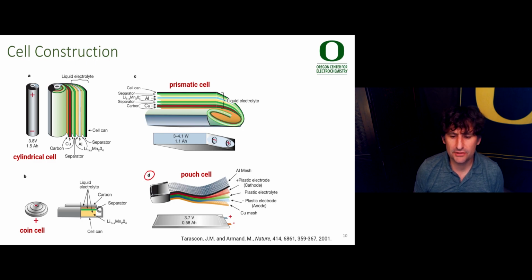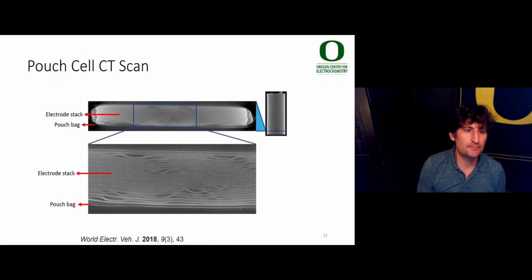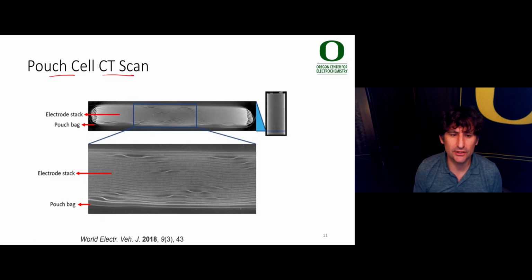And here D, the pouch cell, which consists of alternating layers that can be repeated multiple times to form the battery cell. Here's actually a CT scan of a commercial pouch cell that I found in the literature, and you can really see how the tabbing works here, connecting all the, for example, positive electrodes and negative electrodes together, and how they're stacked and interleaved, coated. Here's the coated electrodes, and here's the separators inside the cell.